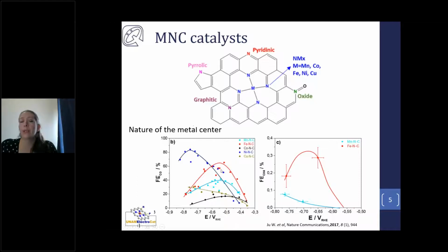And we can form CO with a decent selectivity. And we can also form traces of methane. These are very, very small amounts, but we could think that we can design the iron sites to enhance the selectivity towards methane. In addition, if we want to reduce CO2 selectively to CO, maybe we can think of nickel as a selected metal, because it has a selectivity of higher than 80% when we use it for CO2 reduction.